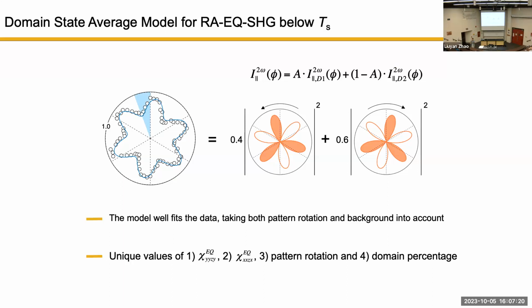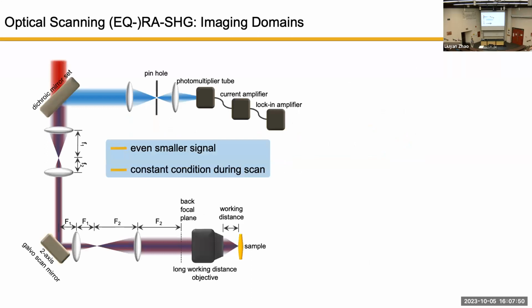But the beam was so big that I cover both domain states. So imagine you have one rotating this way, the other rotating this way, and you add them together. Then the valley cannot happen, because the valley happens at a different angle for different domains. So the data was fitted by a weighted add-up of the two cases. For this particular temperature's data, it's 40% counterclockwise and 60% clockwise adding up to give this data.